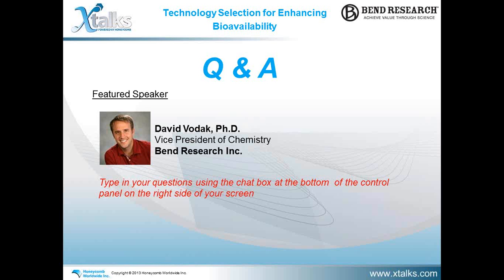Great. Okay. Thank you. Our next question here: can the same formulations be used for spray-dried dispersion and hot melt extrusion? Sorry, I missed part of that question there. Can the same formulations be used for SDD and HME processing for amorphous formulations? I guess it's possible. Typically, the types of polymers that you would want to use for an HME tend to be things that have better thermal stability than the cellulosics. Things like the PVP-VA, those types of systems are typically more suitable, but you can also make spray-dried dispersions out of those. The only difference I would say, based on the process, is that due to the different quenching rates, sometimes it's harder to get a metastable, stabilized amorphous system in an HME.